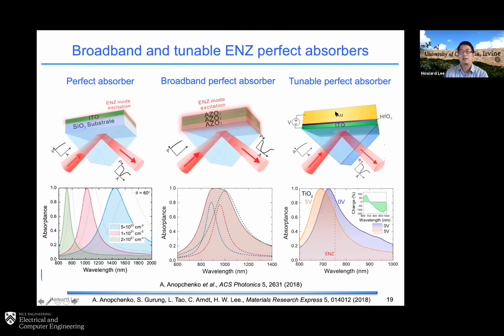And at the same time, we're also able to demonstrate a tunable structure, as I mentioned to you, making a MOS field effect structure. You can tune the property, and we are able to tune the absorption band. For example, by applying a voltage, you can tune this absorption band by maybe 15 nanometer. At the same time, the absorption change could be more than 100% here. So this is more or less some of the linear properties of the ENZ material, and some of the tunable properties as well, that I showed you here.